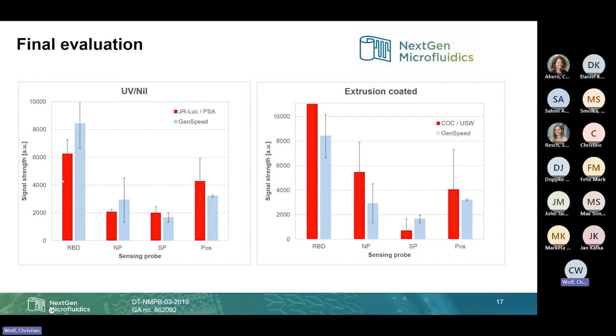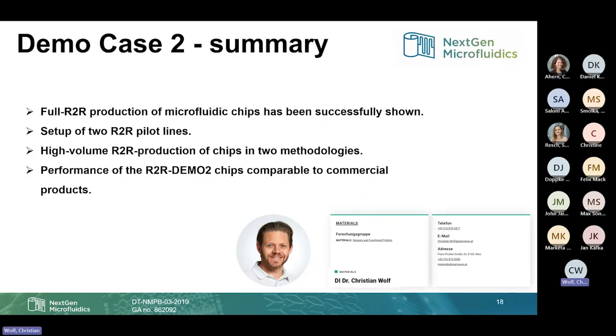in summary, you can say that the roll-to-roll chips' performance is in the same order of magnitude as the commercial chips concerning signal height and signal quality. Some a little bit higher, some a bit lower, but overall I would say the signal performance is comparable, which was, of course, a nice success of our demo case. And that also already brings me to a short summary.